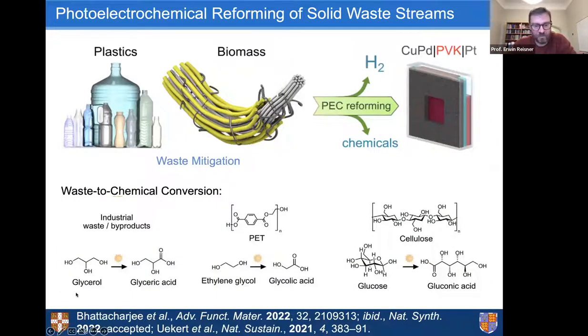Again, here, also no details. Glycerol, we were interested because it's a byproduct from the biodiesel industry. If you produce a ton of biodiesel, there will be about 100 kilograms of glycerol as a byproduct. Ethylene glycol can be sourced from polyethylene terephthalate plastics, PET. So if you hydrolyze this under alkaline conditions, you will source ethylene glycol. We can oxidize this to glycolic acid. And also cellulose from lignocellulose can be broken down under alkaline conditions to glucose. And this then also we can oxidize, in this case, to gluconic acid.